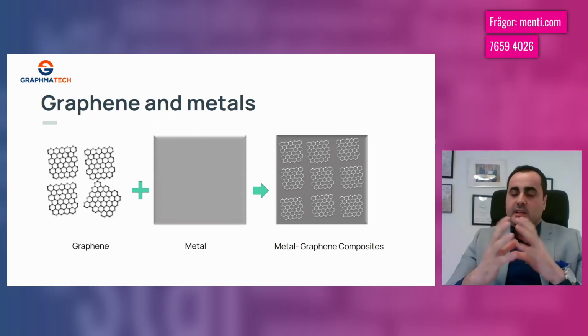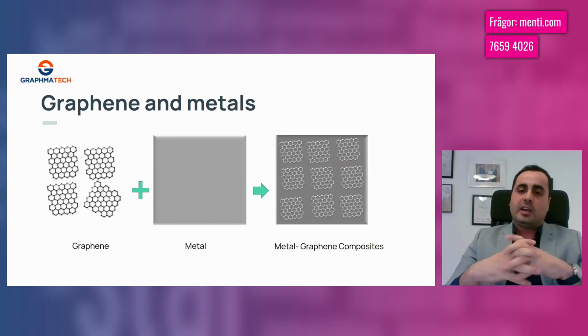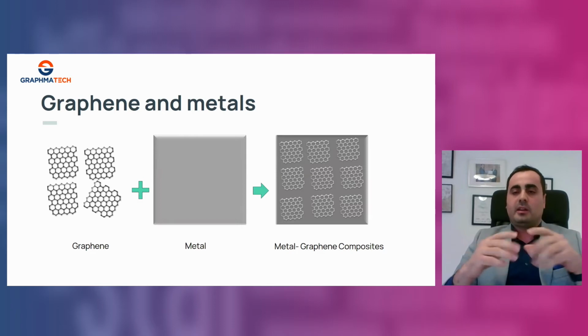So when we mix these two materials, if you get really nice dispersion, what you get is a composite. There is a possibility that the graphene will chemically react with the metal matrix, and then what you get is like an alloy. However, there's degradation of graphene happening if it chemically reacts with the metallic matrix. So let's assume that the graphene is not interacting chemically, it's distributed, and then we are getting a nice composite. We call it a metal graphene composite, okay?